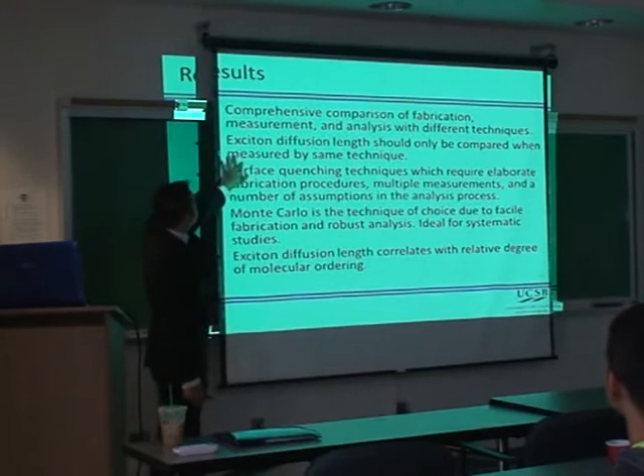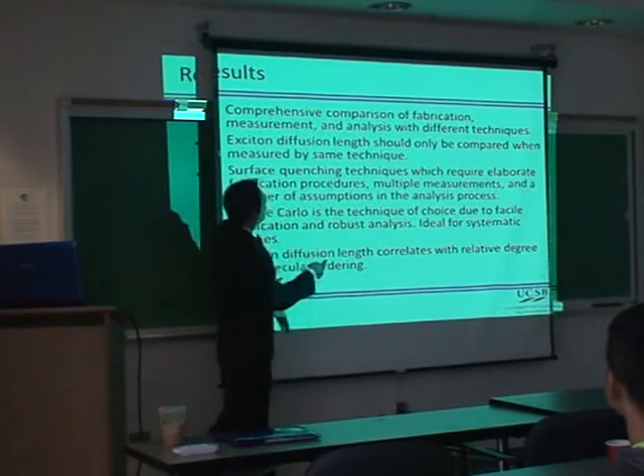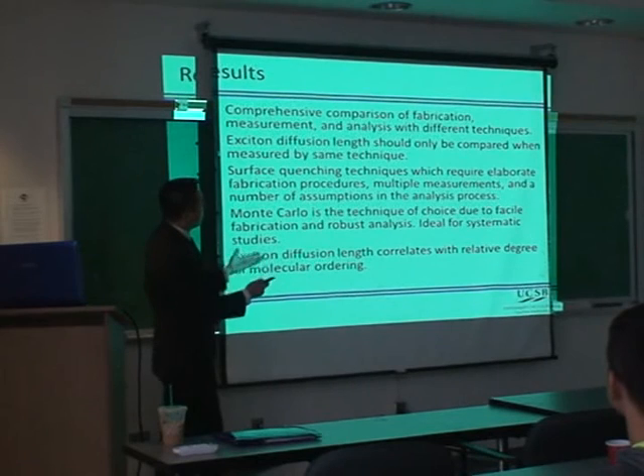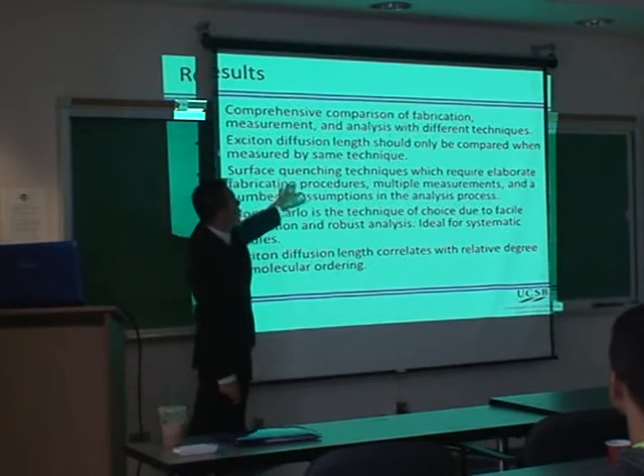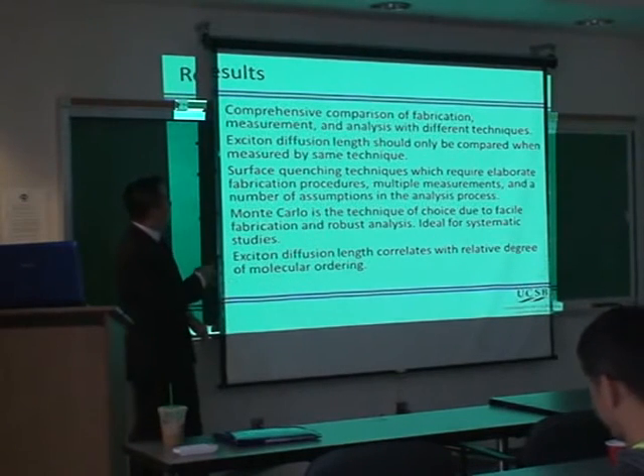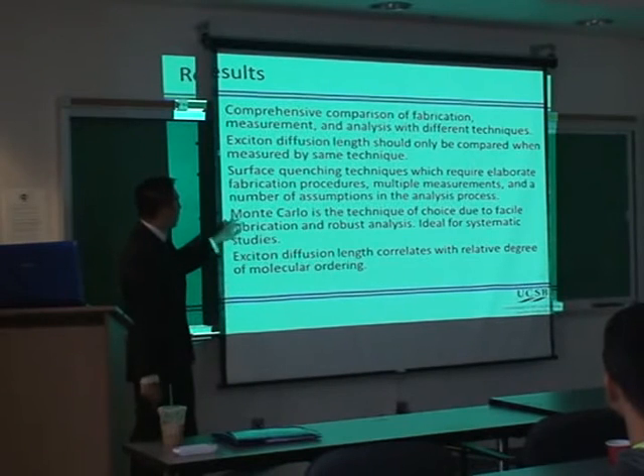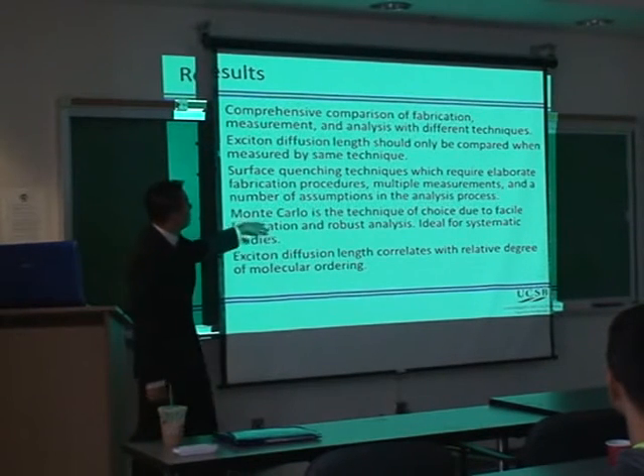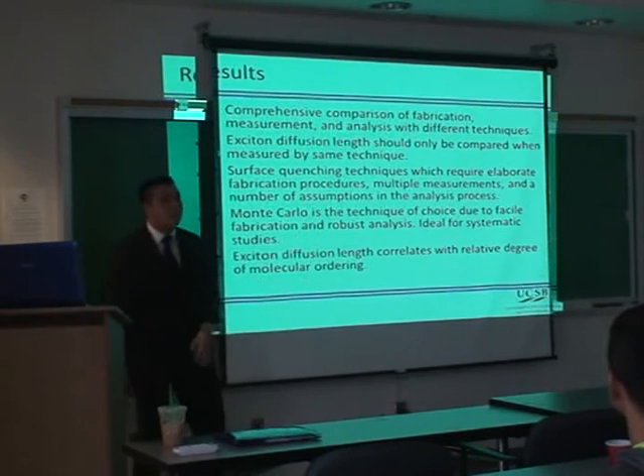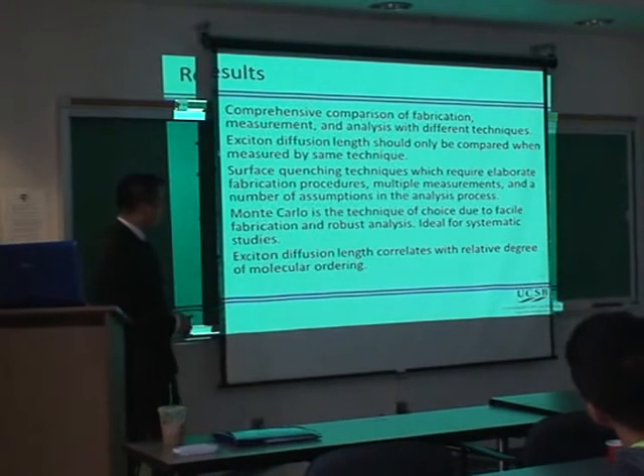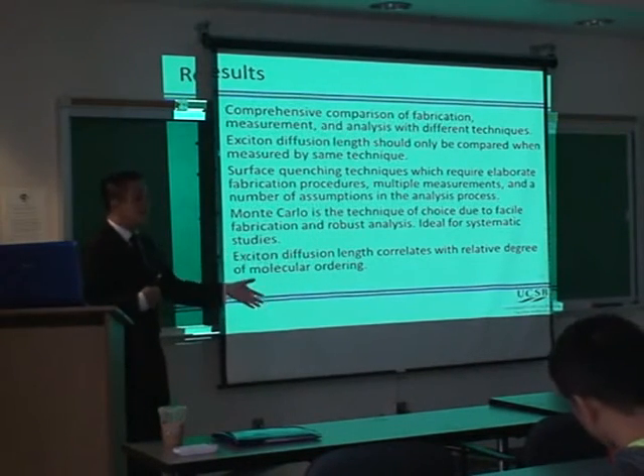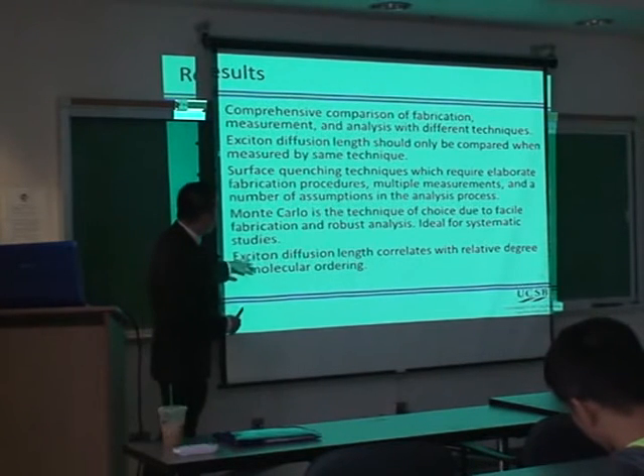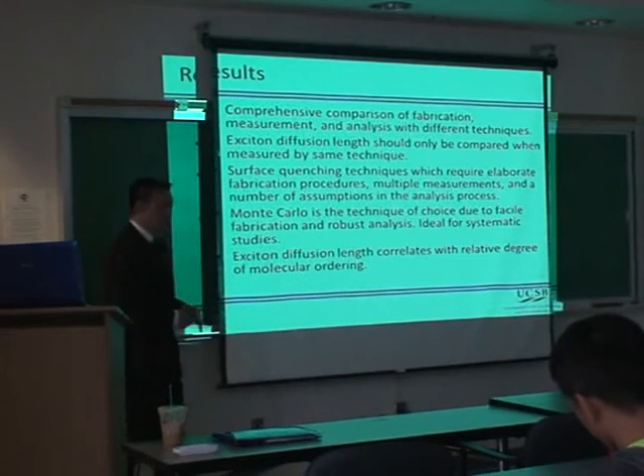In addition, my work showed that the exciton diffusion length should only be compared between the same technique, just to be safe. I also found, from experience, that the surface quenching techniques are quite demanding. They have an elaborate fabrication, multiple measurements, and a number of assumptions in the process. However, Monte Carlo simulation is a really good technique because it can be done very quickly, and you can do a lot of different systematic studies. And finally, we find that the exciton diffusion length correlates with the degree of molecular ordering.